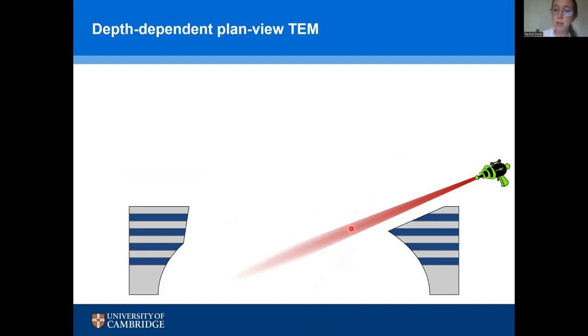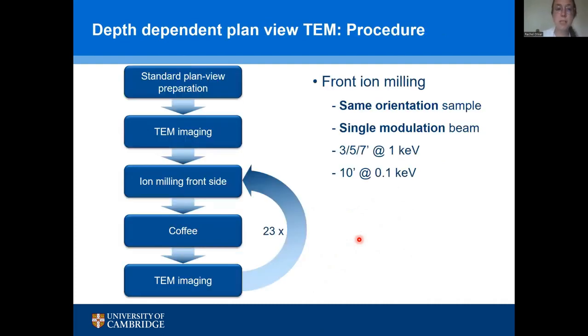So if I move the ion gun, now the region that's thin is going to be this second layer here. And we can take this approach and actually sample all the way down through a multi-layer, taking the material and milling away more and more, and then returning the sample to the transmission electron microscope. So the whole process, we start off just making a normal plan view TEM sample. We look at it in the TEM. Then we do this extra ion milling step from the front side. We put it back in the TEM and see the next layer down, and then keep on repeating. Fabian, who's the postdoc who did this work, says he did this 23 times, this whole cycle. That's why there is coffee in the cycle as well.